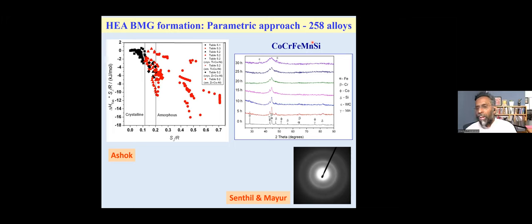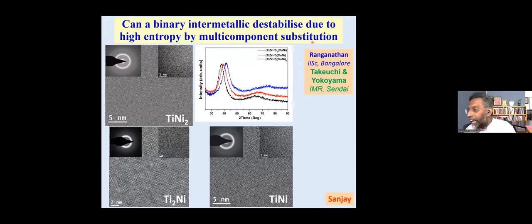And we are now able to make amorphous alloys, which we call glasses, or bulk metallic glasses. And such alloys can be made by increasing the entropy of the system. We call them entropy stabilized amorphous materials. And one can also, very interestingly, take an intermetallic compound. A compound is mostly an ordered structure. But if I take a compound and add a number of elements, for example, take TiNi2, which is a compound, and in addition to just titanium, I add some zirconium and hafnium. In the place of nickel, I also add copper and make a multi-component alloy. And this multi-component alloy is completely amorphous now. You see that I'm able to take an ordered compound and destabilize the order just by adding elements to it, by increasing the entropy, and then get a completely amorphous material.